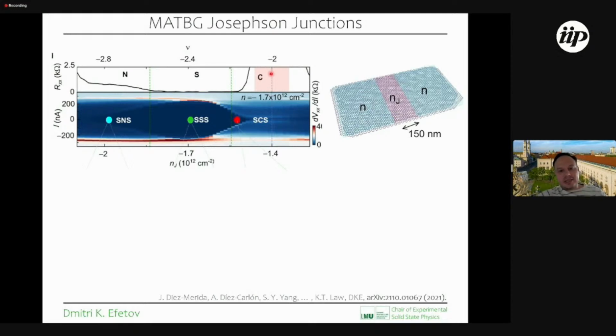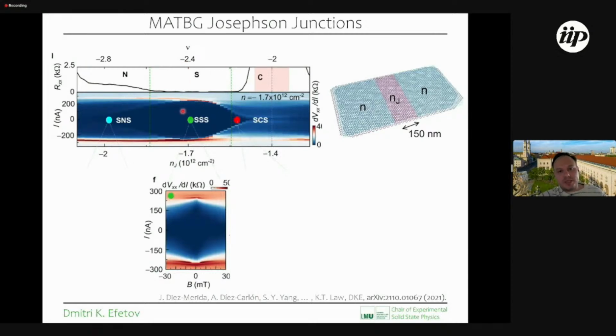And what we find is that the different junctions that we form in the process have very peculiar properties. So for example, if we zoom in on a junction which was created at this density, this is really a proper SSS junction, meaning that it's no junction at all, if you want. This is really just one big homogeneous superconducting state. And as you can see, if we measure dV/dI as a function of current and magnetic field, we just find the critical field and critical current, which is identified by this diamond shape, but we don't find any signature of any Josephson junction in the system.